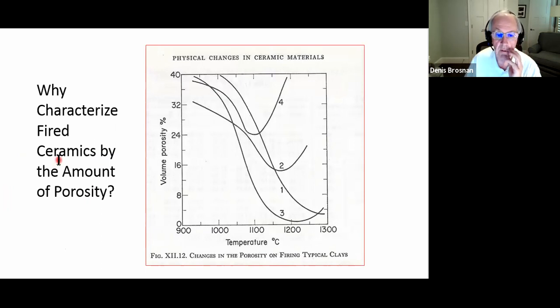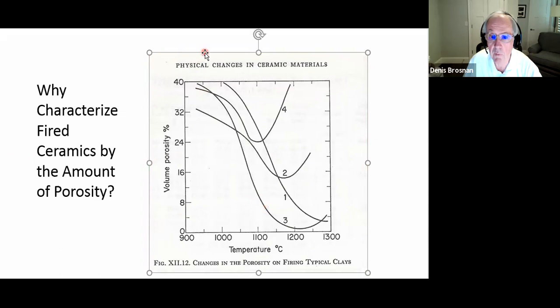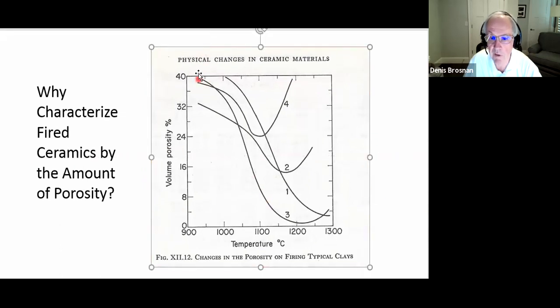Well, why are we concerned about density and porosity? This is a graph of porosity volume versus firing temperature for various fire clay ceramics. Remember, fire clays are substances that usually contain aluminosilicates or kaolinite type minerals. And you can see, just following one of these graphs, as we raise the firing temperature, as we get above about 1,000 degrees C, then rapidly we're going to get a reduction in porosity. There's an accompanying shrinkage, an accompanying increase in density that we have in the ceramic. So that's very typical behavior for a vitrified ceramic.